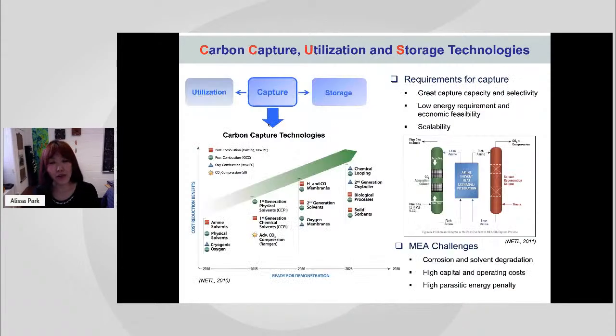One thing is that these liquid solvents I just introduced, like MEA, monoethanolamine, or any of the amine-based liquid solvents, you cannot use in pure form. Most of these amines are dissolved in water, and this aqueous solvent is used in CO2 capture. Since the amine concentration is maximum 30%, now you have 70 to 85% water going along for the ride, going to the red reactor, the green reactor, back and forth. And because the heat capacity of water is so high, a lot of energy is just lost heating up all that water and cooling it down, heating and cooling it down.